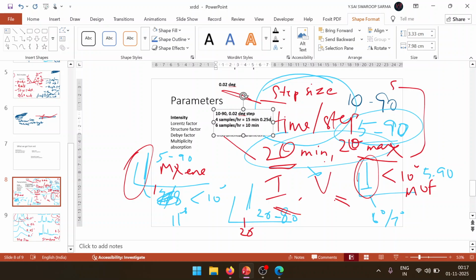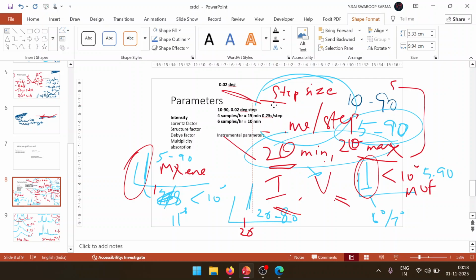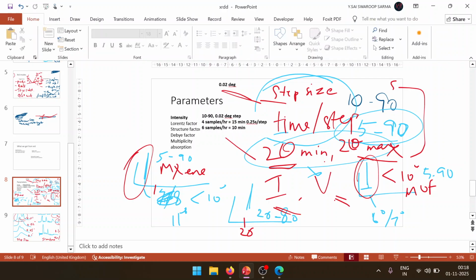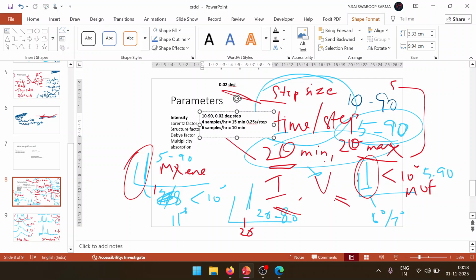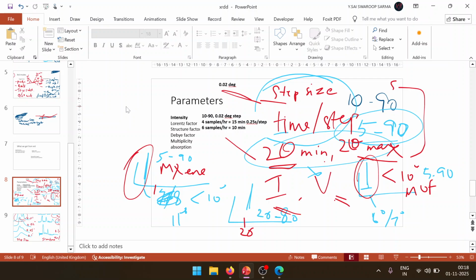It's 0.25, if I remember correctly. Oh sorry, not degrees. This is seconds per step: 0.25 seconds per step. So you can use this as a ready reference if you don't want to do any hard work or reading. So 10 to 90 with 0.02 degrees per step and 15 minutes per sample should be good enough. Also depends on the instrument, but it should be workable.